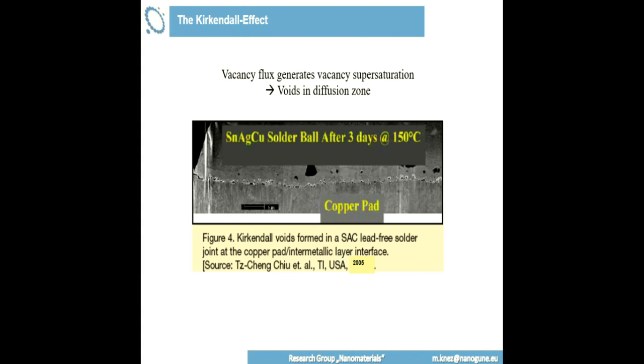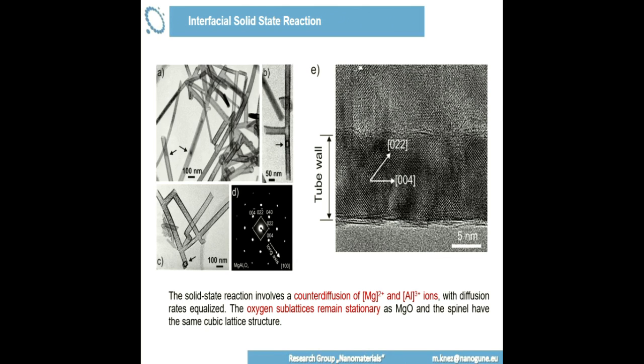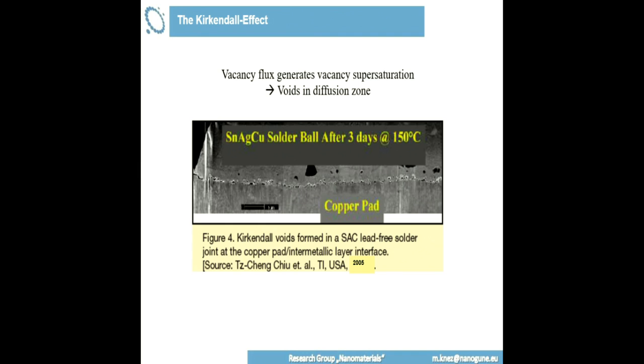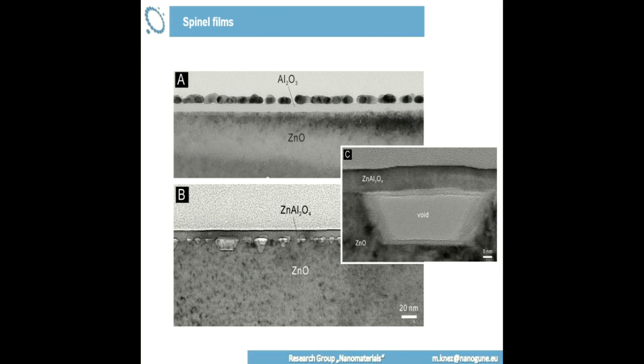And what happens here is also diffusion. It's a very, very similar situation like here. Just this diffusion is not equilibrated. So if you do an ALD coating, for example, you have zinc oxide and you coat with aluminum oxide and you heat it up, what will happen is that you have voids. And this is the Kirkendall effect. It means you have a diffusion of materials which is not equilibrated. In an equilibrated case, no voids. In an unequilibrated case, you have voids.